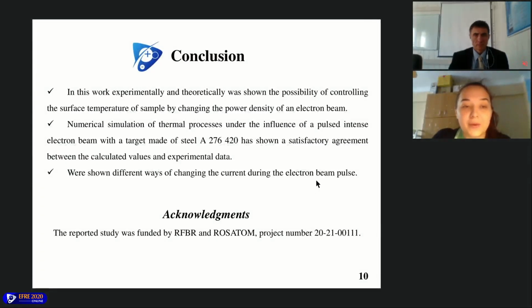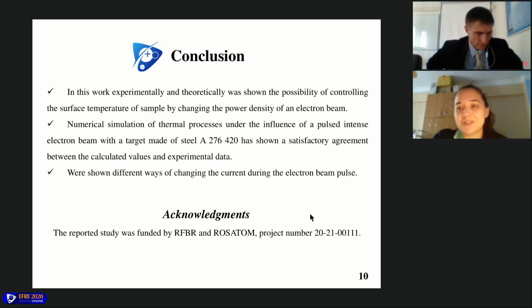In conclusion, I want to say that in this work, the possibility of controlling the surface temperature of a sample was shown experimentally and theoretically, and numerical simulations show a satisfactory agreement between the calculated values and experimental data. Also, in this work, different ways of changing the current during the electron beam pulse and changing the form of the power were shown. Thanks for your attention.